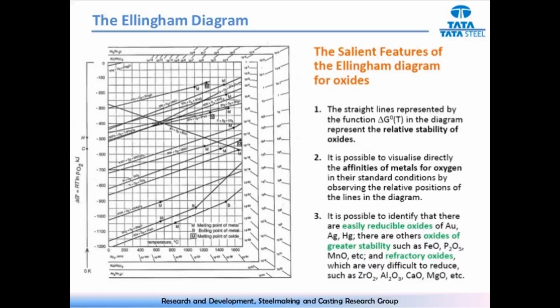It is a straight line with a negative slope. In this case, del S is positive, as 2 moles of carbon monoxide gas are formed by the consumption of 1 mole of oxygen gas. So, it indicates that carbon monoxide is more stable at higher temperature.